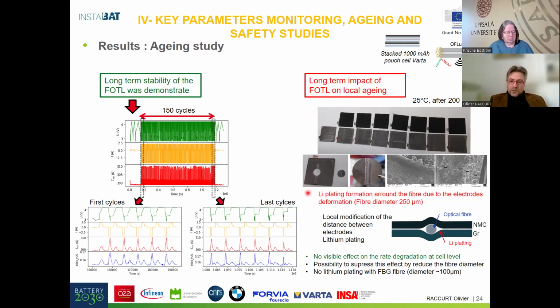It's very local, but there is some question about how we can limit this effect. One solution is to reduce the diameter of the fiber, because, for example, for the FBG fiber, we don't see this phenomenon, but its diameter is smaller than the FOTL sensors, around 100 micrometers.